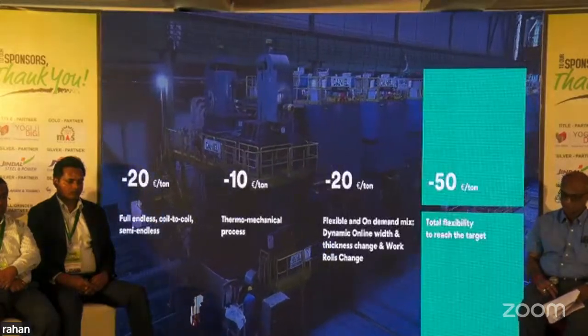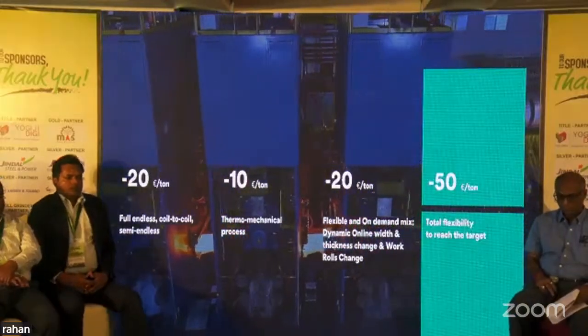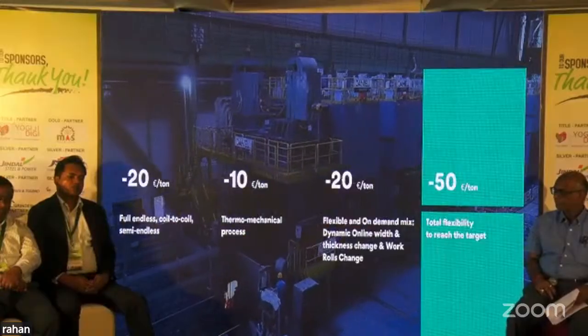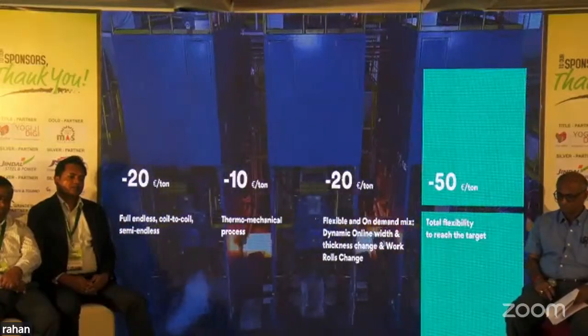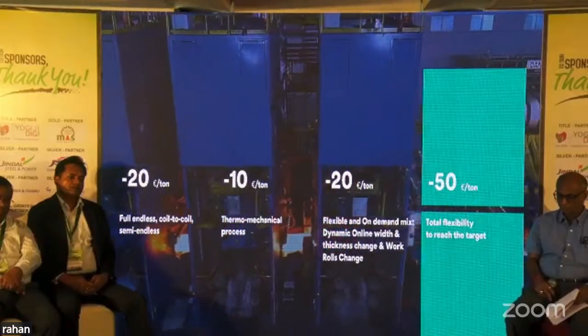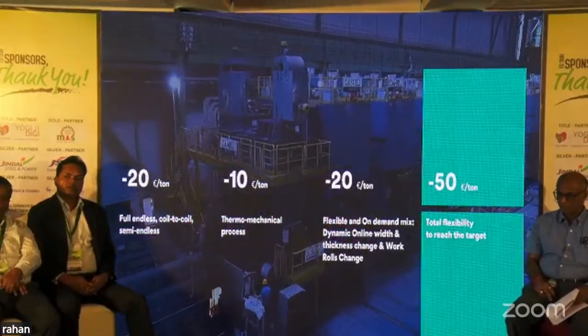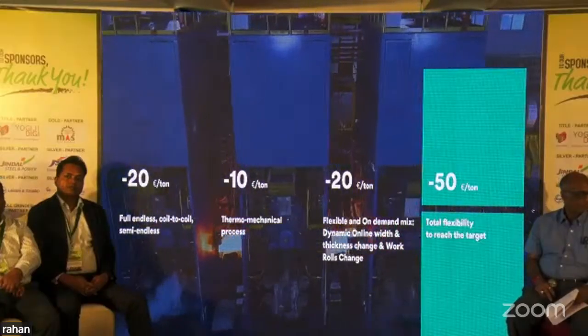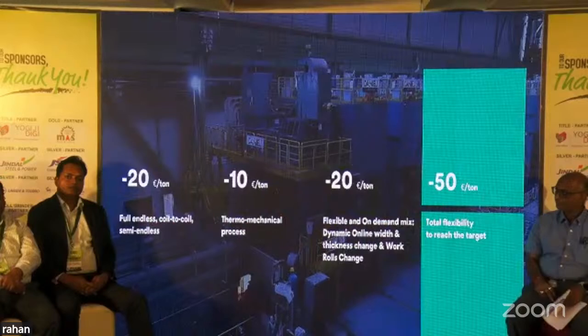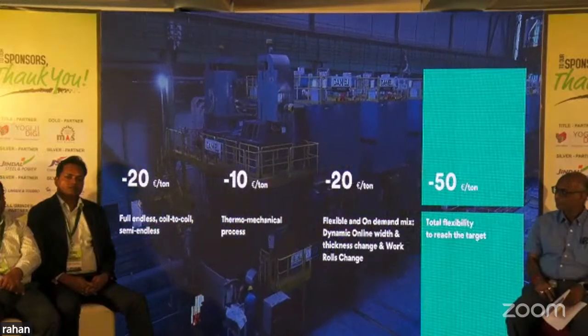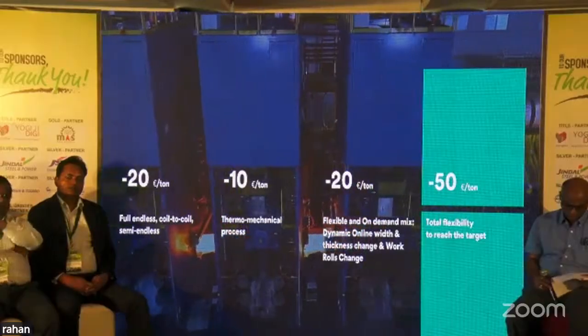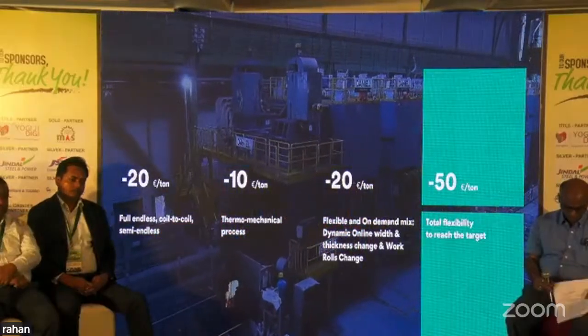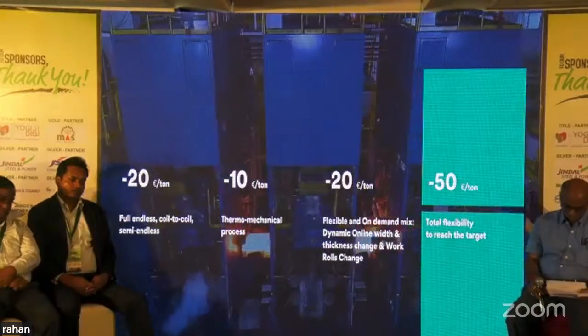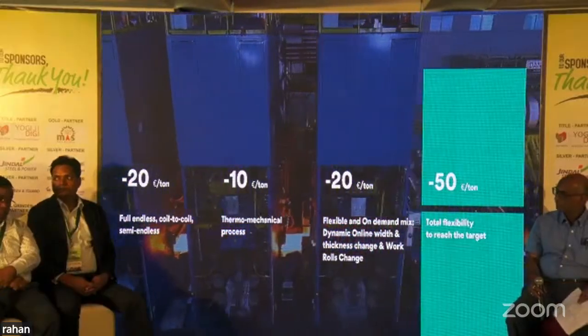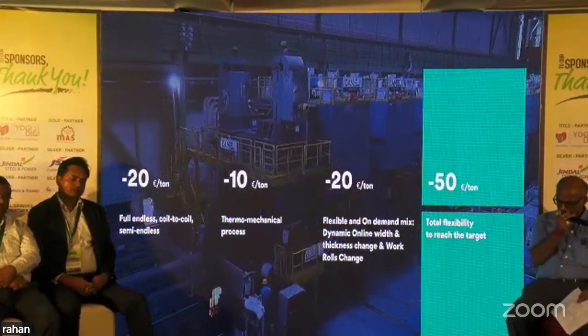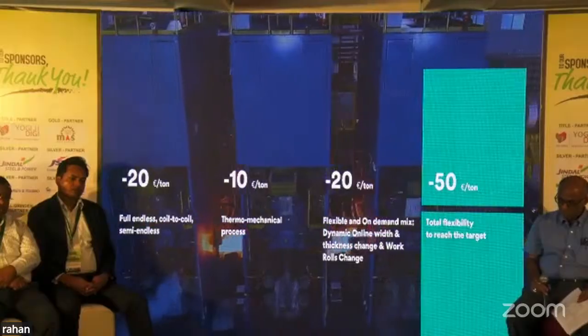And these are a few numbers, like the OPEX benefit, which you can get is around 50 euro per ton. I would not like to speak more about it, since it requires a little bit more elaboration. But what you can see is that the benefit of 3 modes gives you a certain amount of savings or efficiency in your operations. The thermomechanical rolling that I mentioned, and the flexibility of reducing the width on line. Also the tunnel furnace gives you a benefit that you need not stop your mill for the roll change. So this way, you will have a substantial amount of euros per ton saving. And when you have euros per ton saving, you are naturally being competitive in the market.